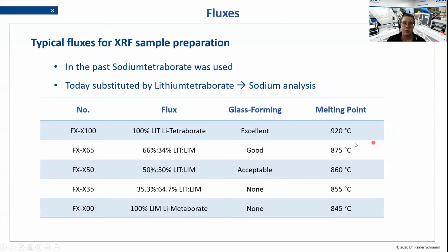So which fluxes are typical for XRF sample preparation? First of all, let's talk a little bit about the past. In the past, sodium tetraborate was used, but today this is substituted by lithium tetraborate. Why? Because we want to analyze sodium, and this will not be possible very easily when you're using sodium tetraborate.